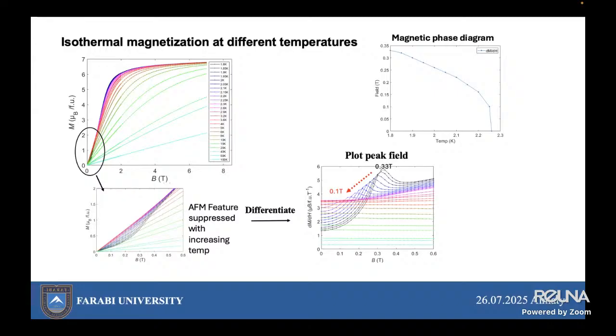In conclusion, this figure comprehensively demonstrates how the antiferromagnetic-like ordering is suppressed by both temperature and magnetic field, and the differentiation of the isothermal magnetization reveals precise field scales of transition. A field-temperature boundary can be extracted from the evolving peak position.